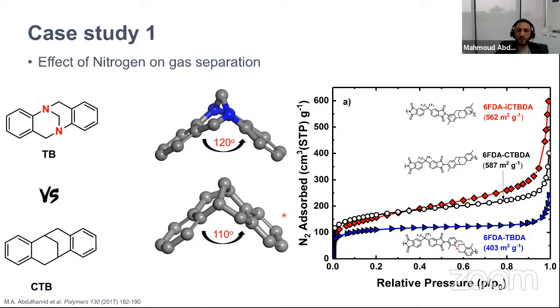So when we did the porosity measurement, we used a technique called BET surface area measurement, where you can evaluate the porosity of your polymers or porous materials. We found that the polymer made with this nitrogen-based unit has a BET surface area of about 400. However, when we replace the nitrogen unit with carbon, the BET surface area goes even higher, around 50% higher. So there is a big change happening due to the presence of nitrogen.